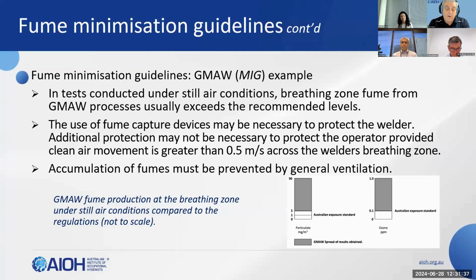Be aware, though, that care must be taken to avoid excessive drafts, as it can remove the gas shielding from the arc and cause welding defects, including porosity. Accumulations of fumes in the workplace must be prevented at all times. And so adequate general ventilation is essential, or otherwise not only will the 1 milligram limit be exceeded, so will the old 5 milligram per cubic meter limit. And next slide, please.